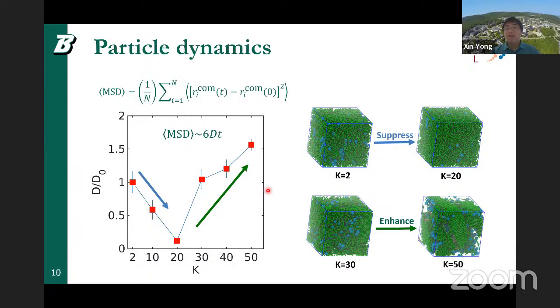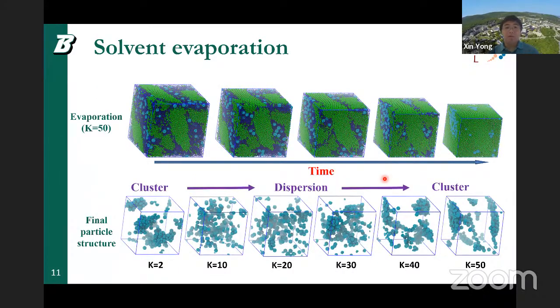And so what that indicates is that the particles start to diffuse more freely when there is microphase separation. That's because this creates a solvent-rich region, and that will facilitate the diffusion of the particles. Now, speaking of the interaction, speaking of the assembly structure, let's look at what happens when we introduce solvent evaporation. Here we model the evaporation very simply by taking out the solvent beads gradually in time.